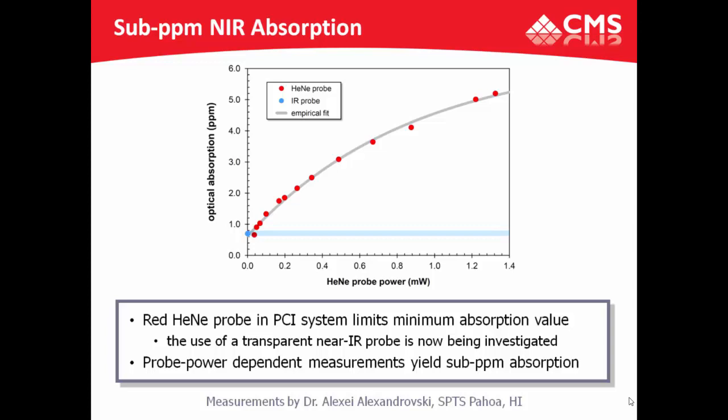I'm going to condense all the results into basically one plot. So it turns out that what's the most exciting scientific advancement? We found out that the way to reduce the absorption in the coating is just to grow them as fast as possible.